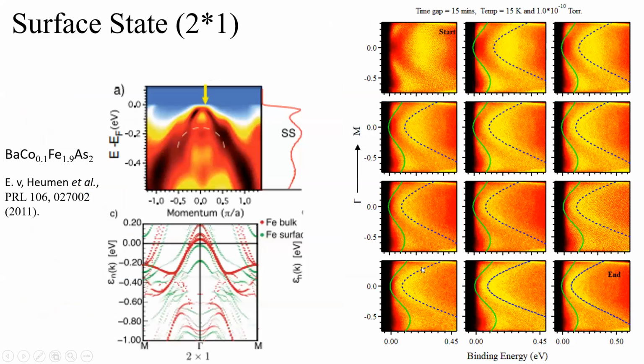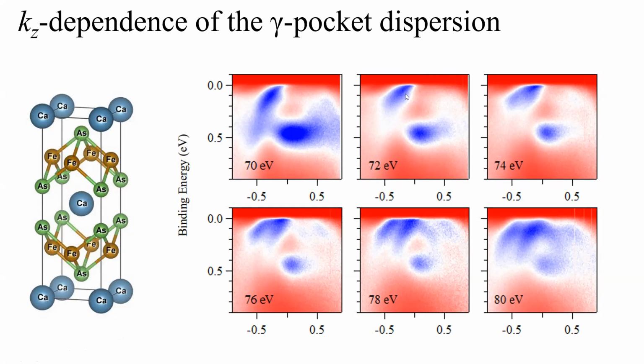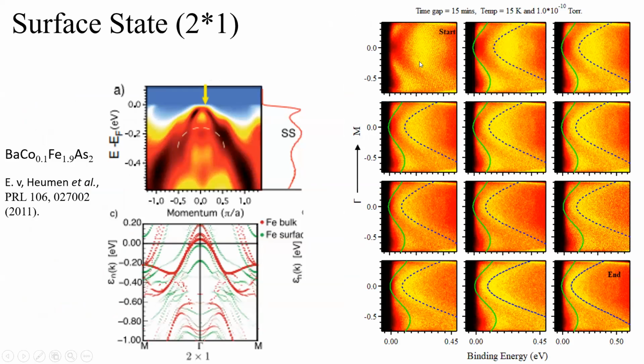This is kind of a bad example for the photoemission spectroscopy technique. What is basically happening is that I did this measurement in our lab at 15 Kelvin temperature at different time gaps. This one is the same gamma band. We have a hole pocket here, the alpha band, and we have a significant amount of intensity at this position also. This intensity is majorly due to the surface state. When we do this measurement, after every 15 minutes I measure the spectrum, and we can see that the position of these bands is shifting with time. So these are basically surface states, and probably because of the oxidation of the surface state, we see this shift with time in this compound.